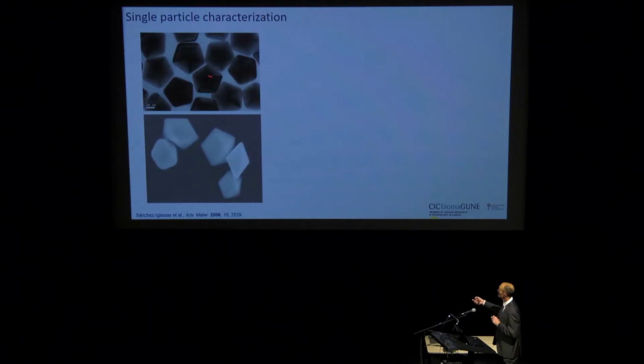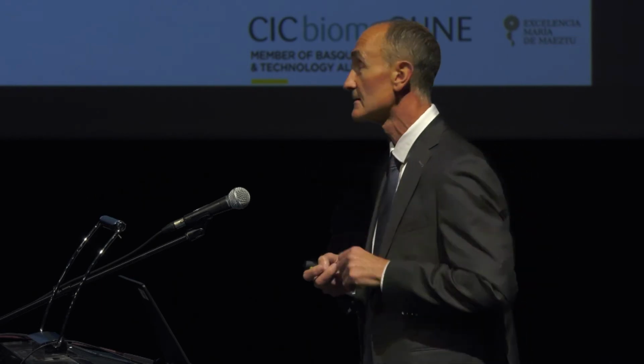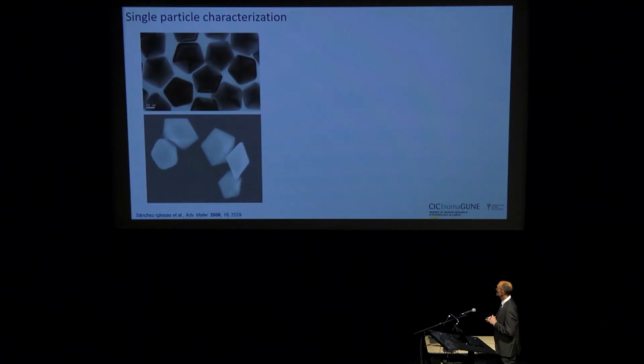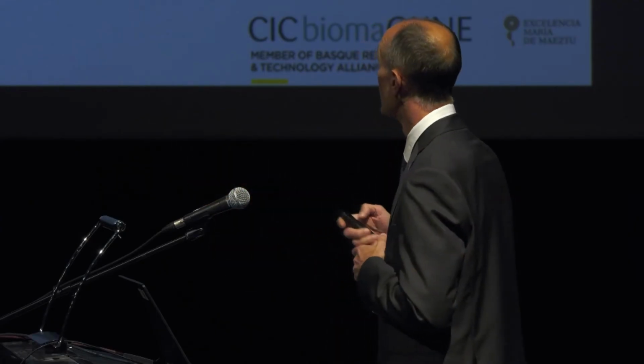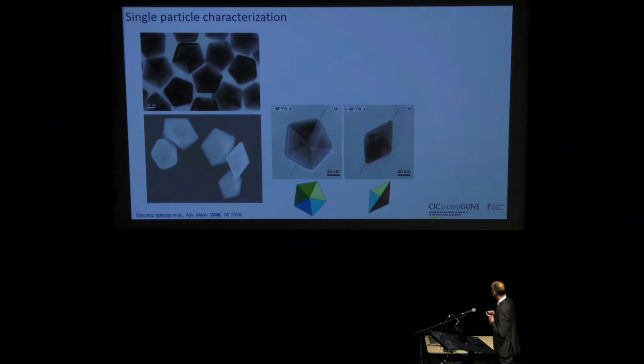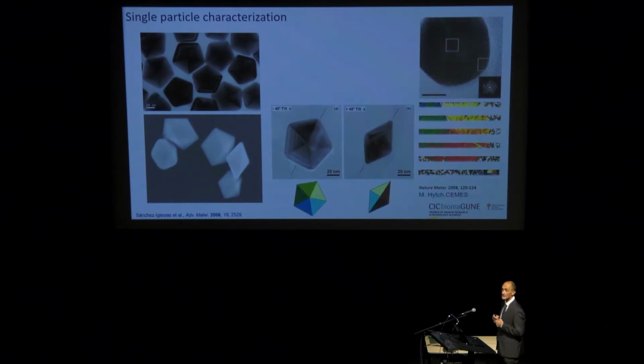The morphology is very similar to the very tiny seeds I showed you a minute ago, but they can grow very large if you find the right conditions for that. So at that time, we did this by using dimethylformamide as both the solvent and the reducing agent. One of my students was presenting this work at a conference, and a scientist established in Toulouse, Martin Hÿtch, came to him and said, can I have a few of those particles? Because I have never seen such well-defined decahedra in large sizes.